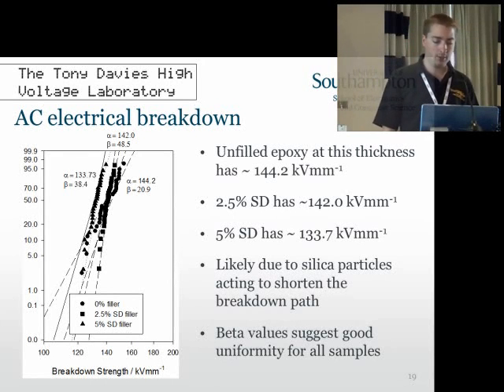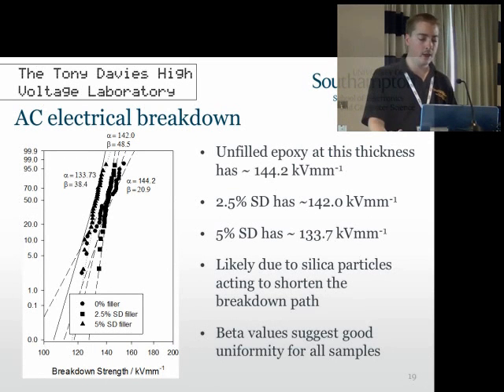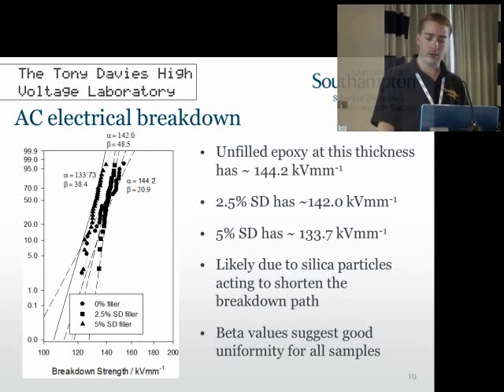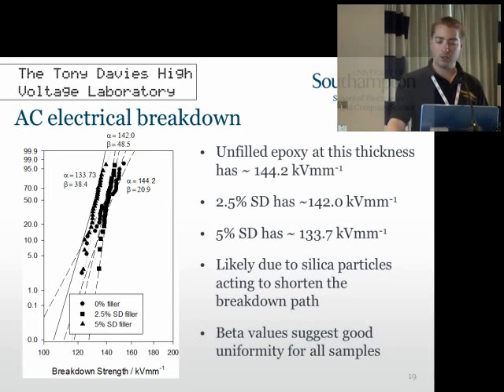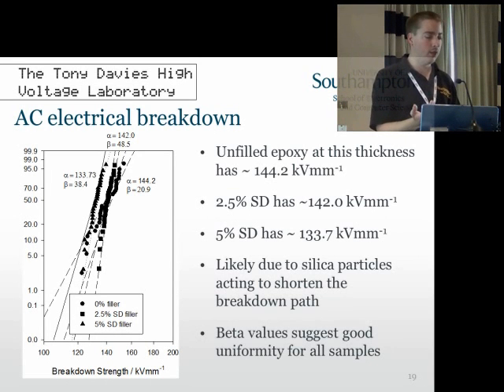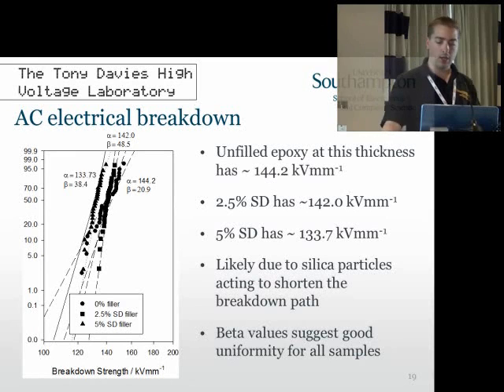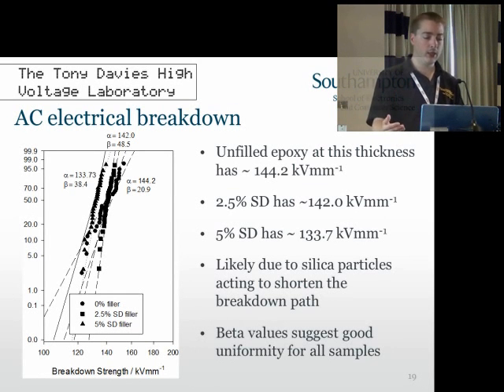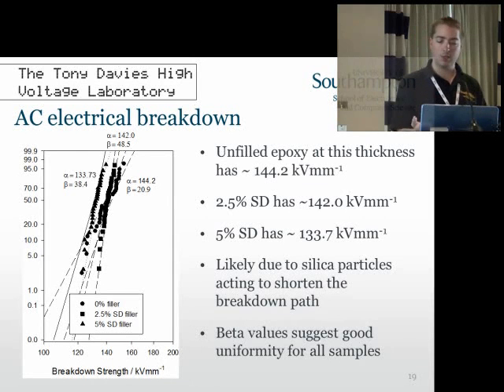Okay, so having a look at our microsystem, we first established that our unfilled epoxy at this thickness had a breakdown strength of 144.2 kV per millimeter, which is about standard for some of the epoxy systems that we've seen before. Once we added a small amount of the micro silicon dioxide, the breakdown strength is slightly decreased. Nothing major, but still worth noting. However, when we then added higher amounts of this filler, we see a much larger decrease. So this is likely due to the particles acting to shorten the breakdown path, and it's jumping between them as it goes through the material. The beta values, however, still suggest that the uniformity of the samples is fairly good. We did see that the beta value did drop from the unfilled epoxy to the filled systems, but we considered this acceptable, as obviously there's going to be some agglomeration in the system, and it's not going to be as perfect as a standard epoxy.